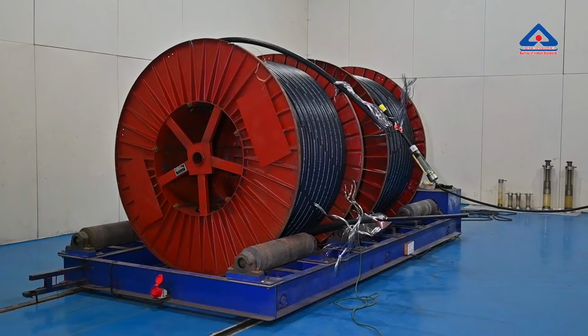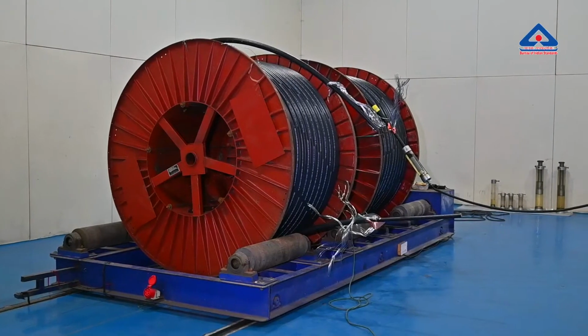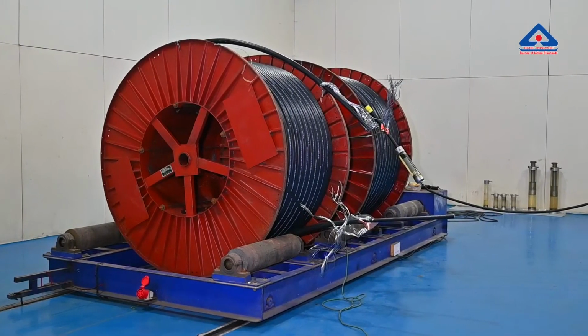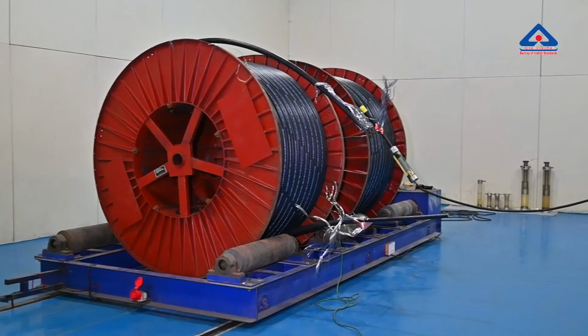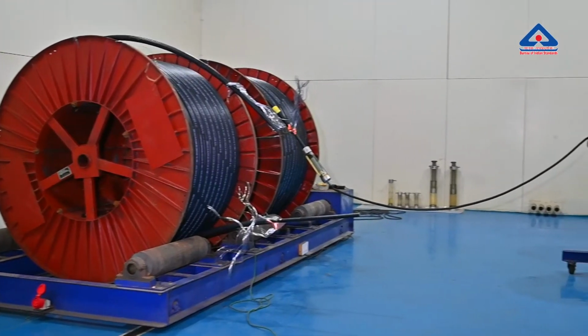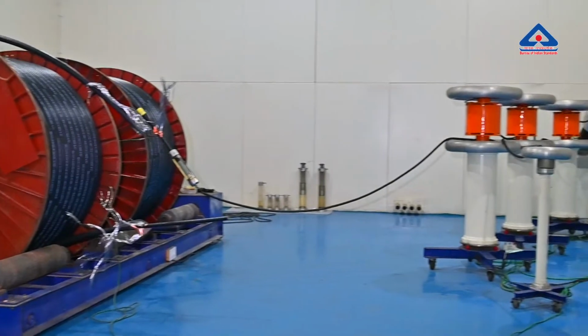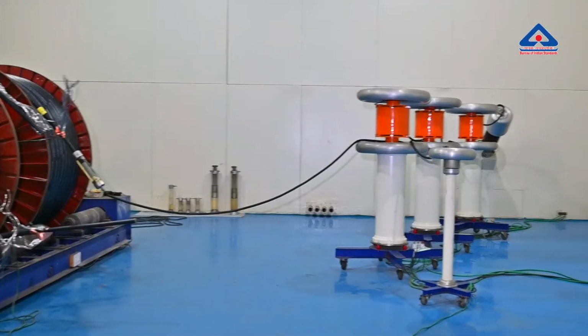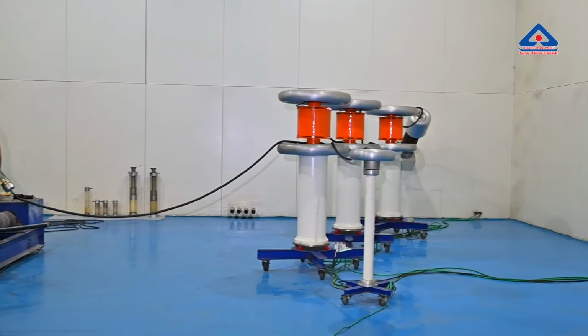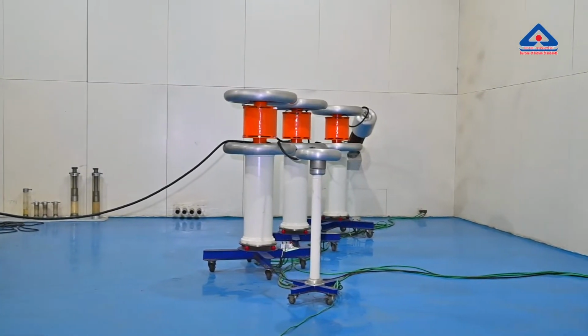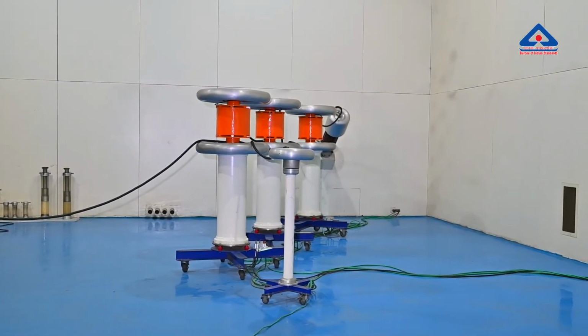Now this is 11 kV cable. Now we are going to conduct the high voltage and partial discharge test. Since this is 11 kV, 21 kV voltage will be applied for 5 minutes. After the 5 minutes are completed, the PD value will be measured at 1.73 U0.